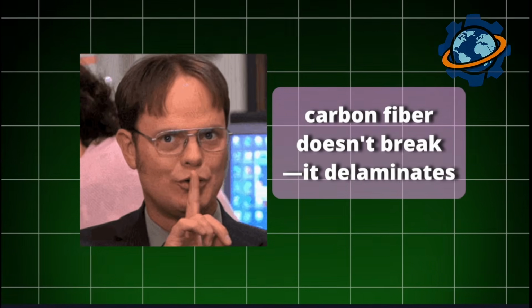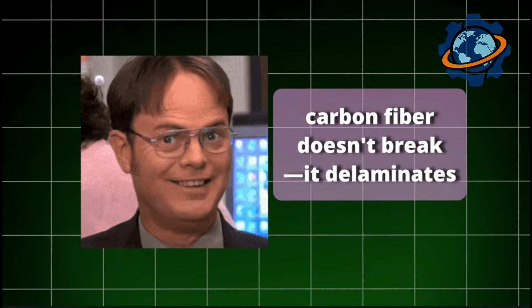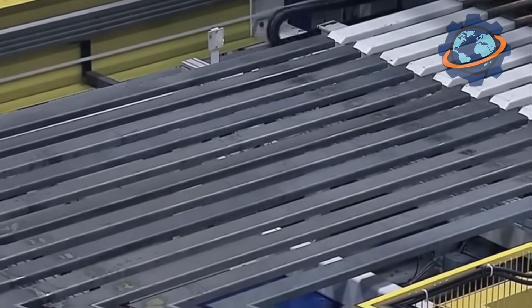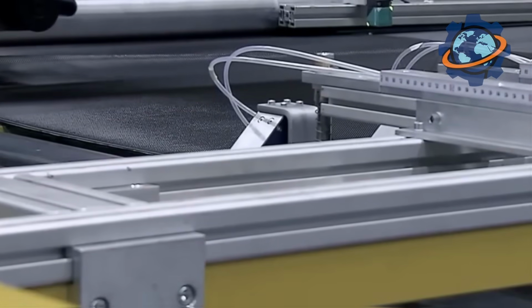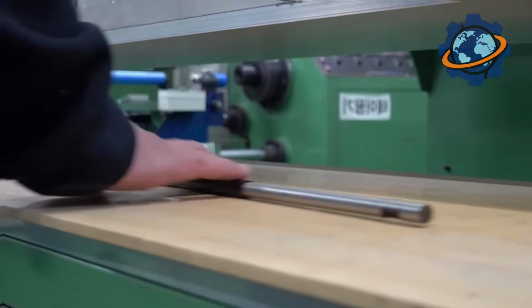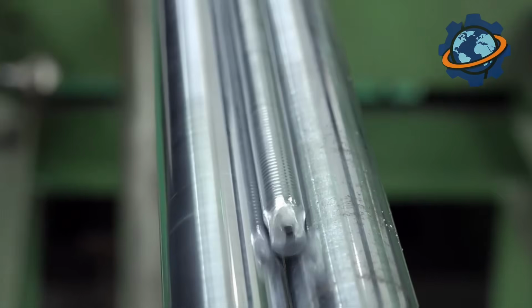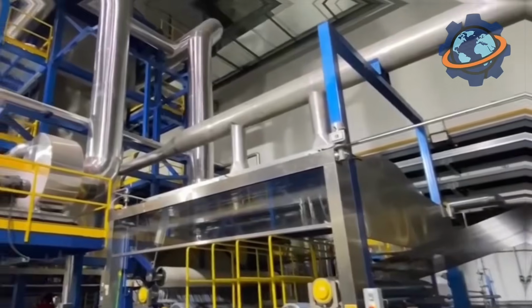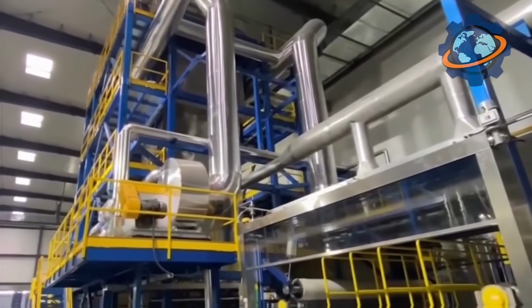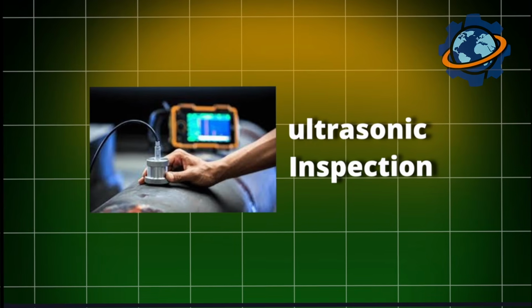So here's the secret promised. Carbon fiber doesn't break, it delaminates. Unlike metal fracturing through crack propagation, carbon composites fail through layer separation. Impact damage creates barely visible surface dimples, hiding extensive internal delamination, while composites require ultrasonic inspection after any impact.